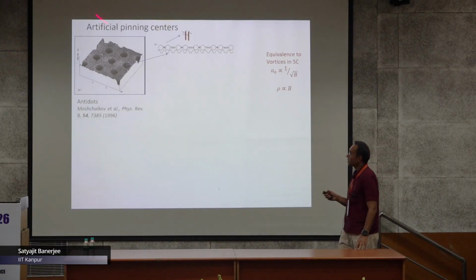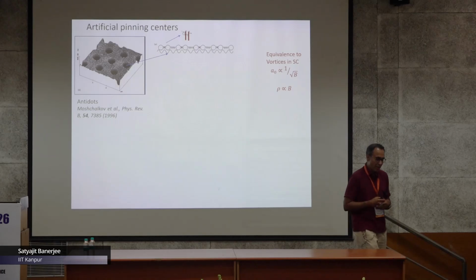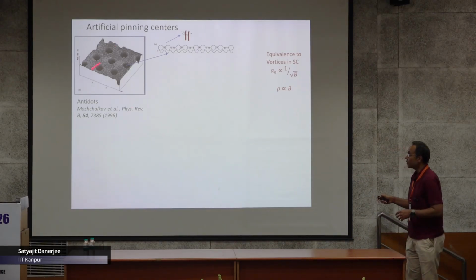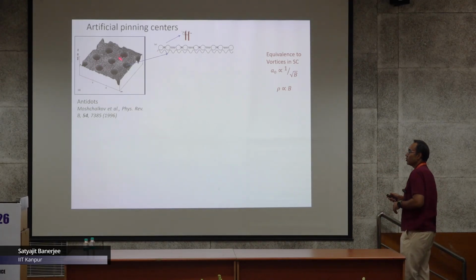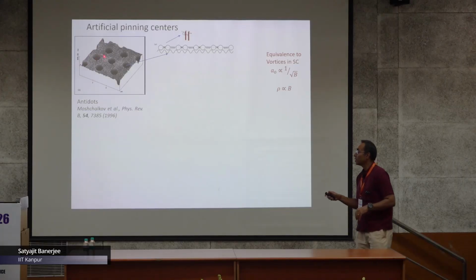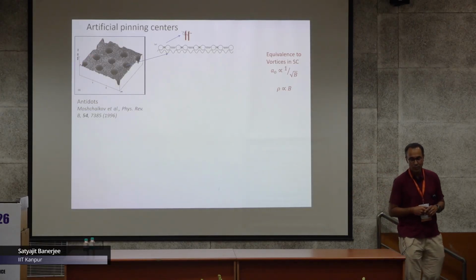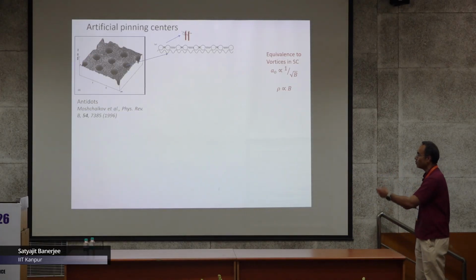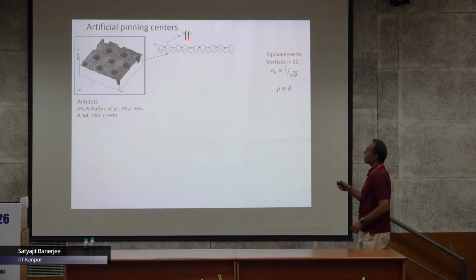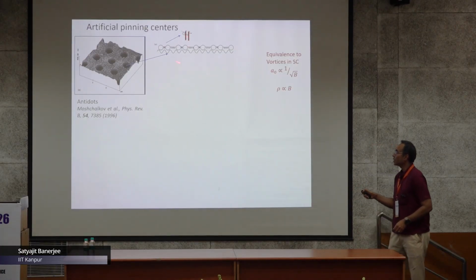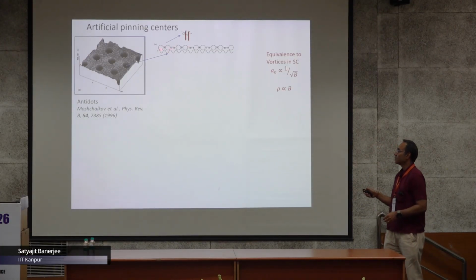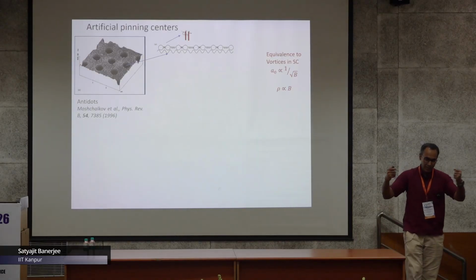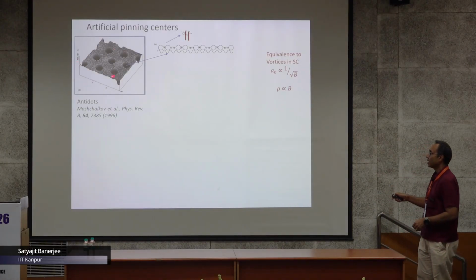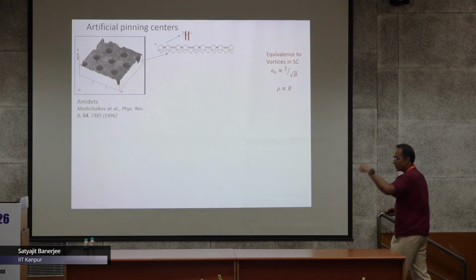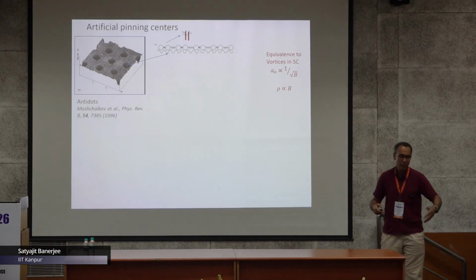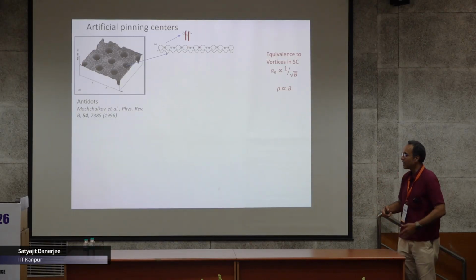This has been studied for some time. People introduced superconductors with periodic arrays of holes inside them, which act as an underlying pinning potential. So you have vortices in the superconductor, like balls with springs inside them, giving an elastic interaction. Artificially, using techniques like e-beam lithography, focused ion beam milling, irradiation, or other complex processes, you can introduce these periodic defects inside the superconductor.